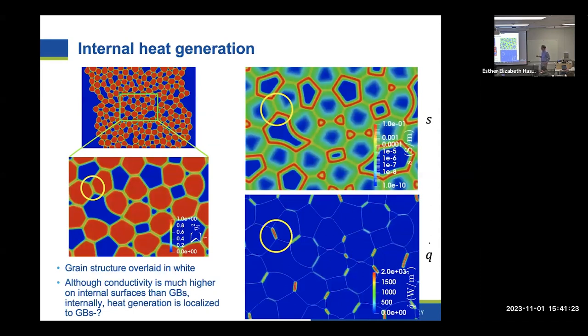Focusing on one particular grain boundary here, highlighted with this yellow circle, hopefully you can see there's a pop of yellow at that grain boundary, which represents an enhanced electrical conductivity at the grain boundary. Still quite a lot lower than the surrounding surfaces, but then if you look at the local heat generation, you see that it's predominantly located at these grain boundaries rather than the surfaces. So this was a little counterintuitive, at least to me at first, because the conductivities are much higher at the surfaces, but the heat generation is predominantly happening at the grain boundary.